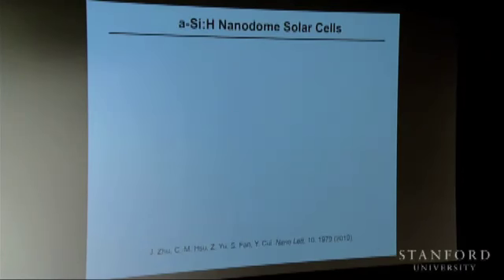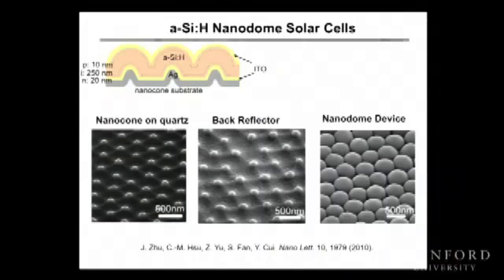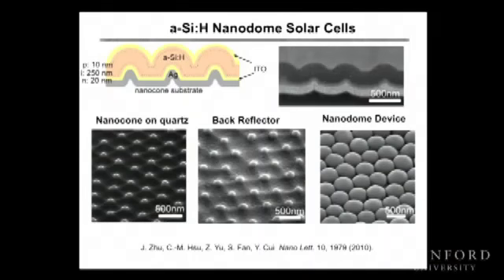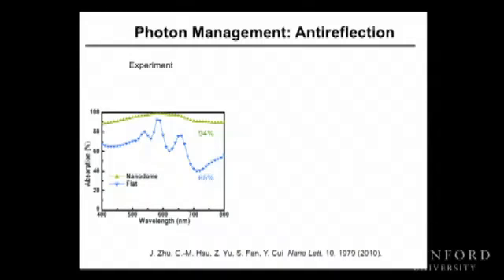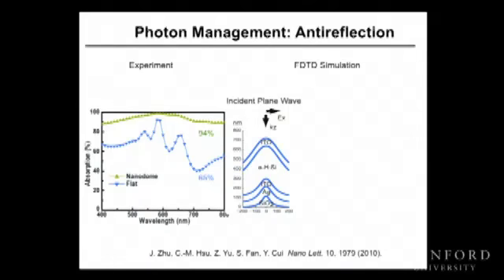So we spent the last couple of years figuring out the light trapping effect, making these solar cells starting from a tiny cone, depositing contact and amorphous silicon, and eventually becoming dome-shaped solar cells. Using this as an example, we figured out for the light absorption, these nanocone, nanodome do have significant enhancement. This is a flat film, absorbing 65% of the light. This is a nanocone, nanodome, absorbing 94% of the light. So we understand this using photonic simulation.